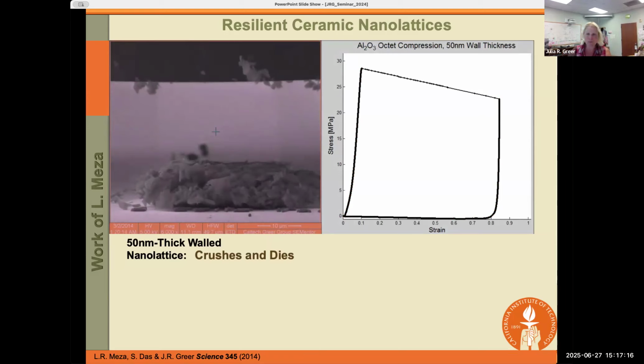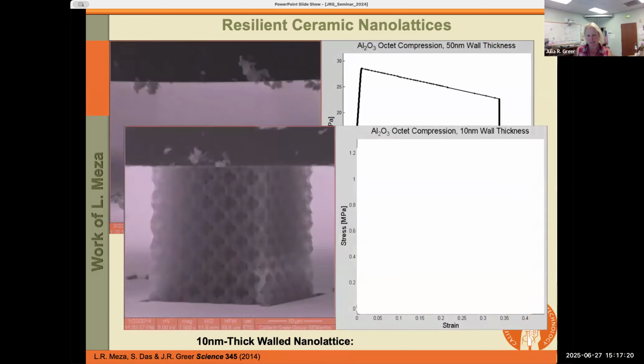I mean, part of being at Caltech is that we don't really give up. So our students are pretty resilient as well. This is the work of my former student, Lucas, who effectively repeated this experiment. But now the only difference is that the wall thickness is reduced by a factor of 5. So now these walls are not 50 nanometers thick, but they're 10 nanometers thick.